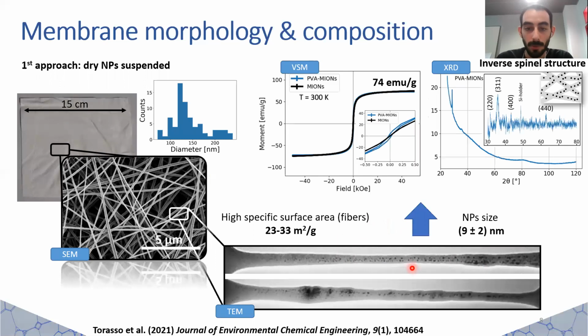Further studies were performed to analyze the composition of the membrane. The magnetic behavior was confirmed by vibrating sample magnetometer, with a saturation magnetization of 74 emu per gram of magnetite, and X-ray diffraction showed the inverse spinel crystal structure within the fibers, corresponding to magnetite.